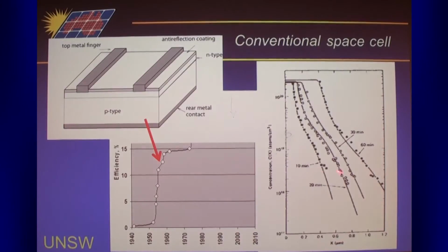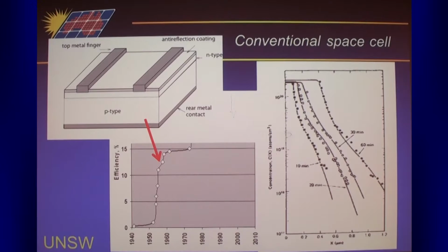So as I mentioned, it had a problem in that it had a very heavy diffusion. So this is phosphorus versus depth. So you notice 1 micron is a long way for these impurities to diffuse into the silicon material. So this doped region near the surface is very shallow, considering that the wafer is several hundred microns thick. So it's only the top percent or so of the device that is actually doped, even though in a lot of these drawings, the regions are looking pretty similar in size.